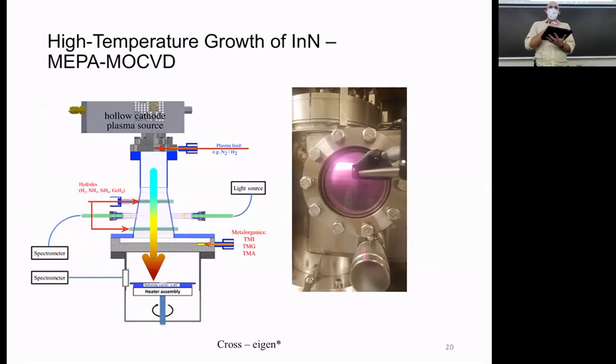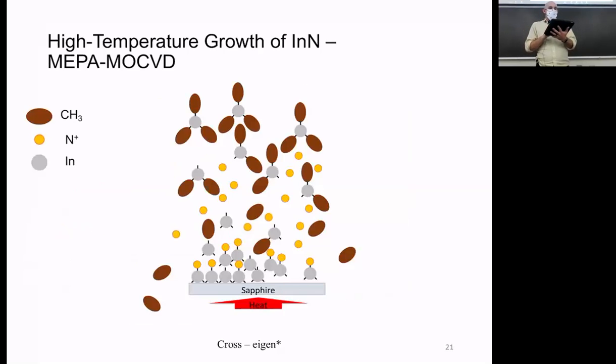So since the other reactor was designed for one specific purpose, it did that well. It's well established. We didn't mess with it. But with the reactor that we wanted to play with, we could make any changes we want. So we did the changes we wanted. And the way that this process works is instead of just using ammonia, we use direct nitrogen ions.